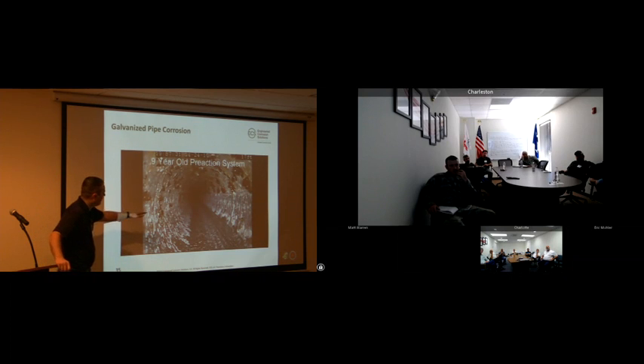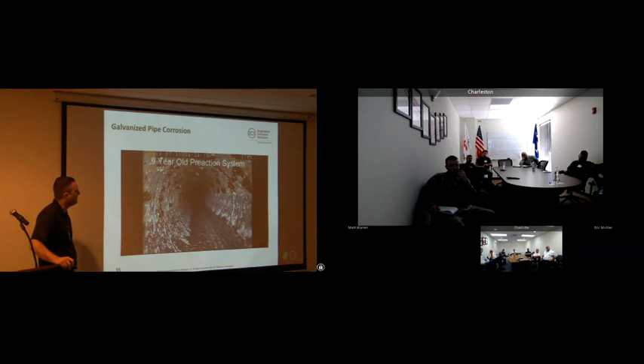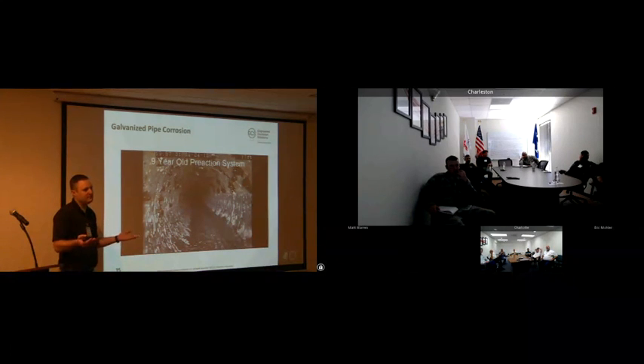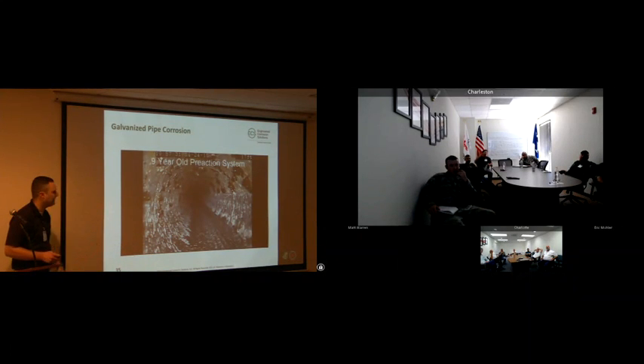But once you get to that second water level where you start seeing those brown and black little bumps, that water probably sat in there for much longer than that. And underneath each one of those is a pit forming and about to happen through the wall failure. So you can see, just given the same amount of time, 9 years versus 10 years, this pipe looks much, much worse than that black steel pipe did.